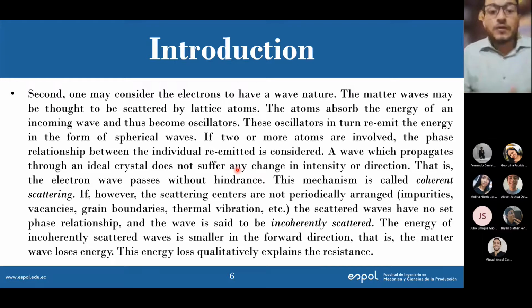So it's obviously a more difficult concept. It's not as easy as saying, okay, I have a particle, the particle is colliding with an obstacle, and yes, that's resistance. Here it's a bit more involved, because I have waves that are scattered by lattice atoms. These atoms absorb the energy of the wave. They start to oscillate. They re-emit the energy in the form of spherical waves. And then I have to see whether those spherical waves are in phase or not. If they're in phase, then I have coherent scattering, then I have conduction. If they're not in phase, then I have incoherent scattering. There is no phase relationship between the waves, and therefore I have resistance.